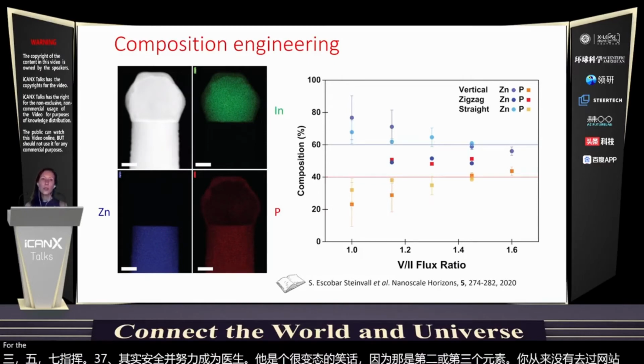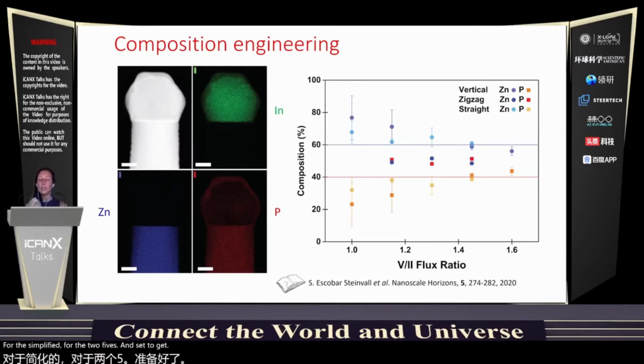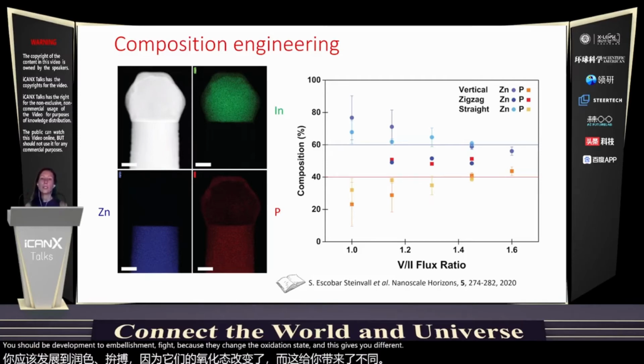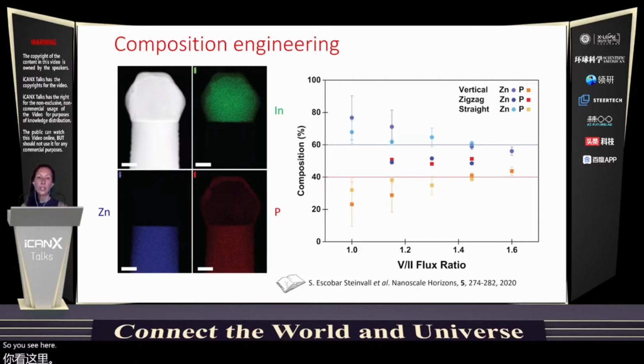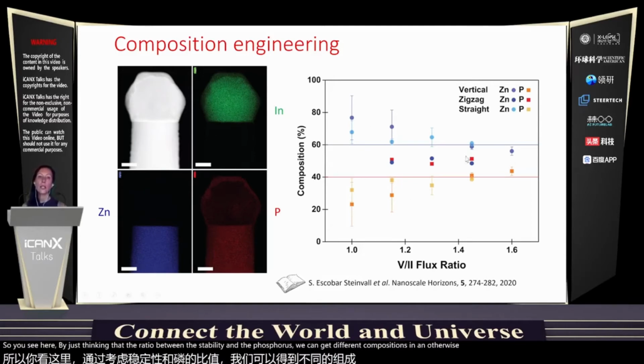For zinc phosphide, a II-V, in fact, you can vary the ratio between the element II and the element V because they change the oxidation state. And this gives you different properties in the absorption coefficient. So you see here, by just changing the ratios between the zinc and the phosphorus, we can get different compositions in the nanowires, and we can control this by just the growth conditions.